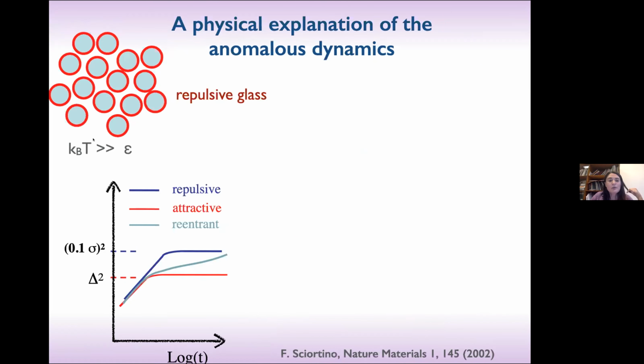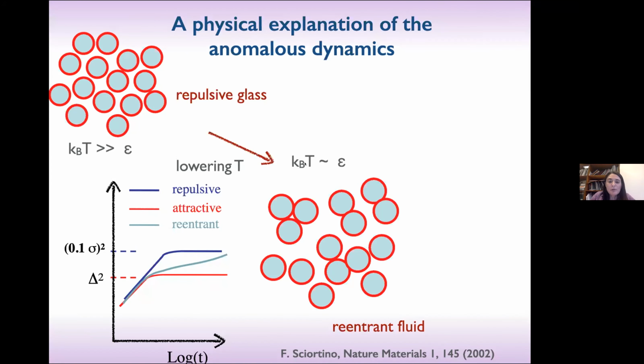And then you can start from a repulsive glass at high temperature. You then start to lower the temperature. And when you go towards a thermal energy similar to the energy of the attractive potential, what happens is that some of the particles will statistically be closer and feel the attraction, some others not.